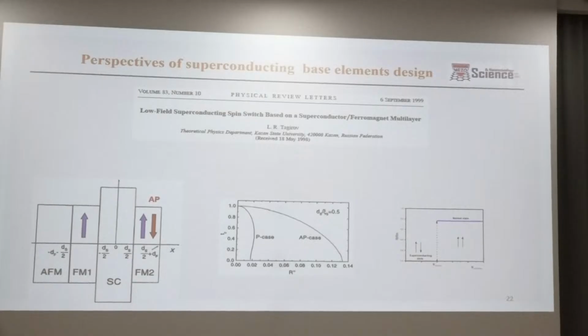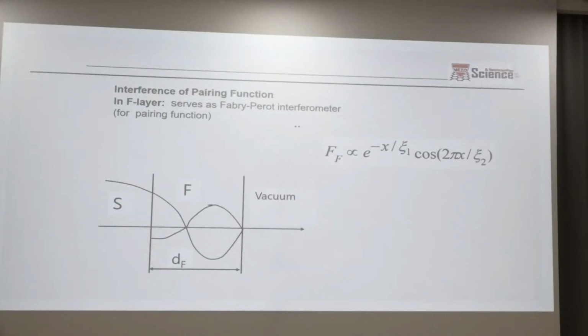And on the basis of this phenomenon, theoretician Leonid Tagirov proposed a so-called spin switch or spin valve, consisting of two ferromagnet layers and in between a superconducting layer. Changing the magnetization of one of the layers looks like changing the thickness of this ferromagnet layer. That's why the ferromagnet layer serves like a Fabry-Pérot resonator for the pairing function of Cooper pairs.